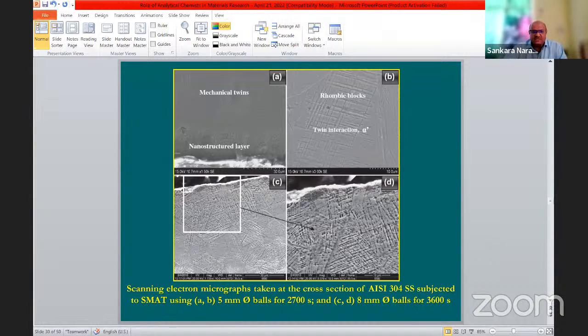We treated by this surface mechanical attrition treatment using 5 mm dia ball and 8 mm dia ball for various treatment time. So if we use 5 mm dia balls, we could be able to see there is some formation of mechanical twins and the formation of nanostructured surface layer. This surface layer becomes a nanostructured layer. So this is the advantage.